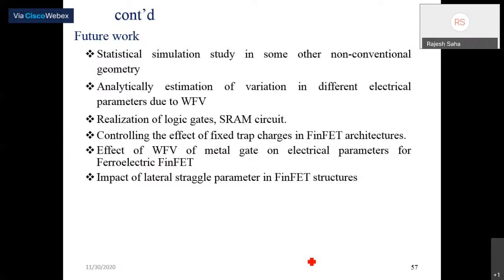See, what does lateral straggle mean? When you do the doping in the source and the drain, then due to some tilt angle and the diffusion process, the source and the drain will extend into the channel, which leads to a reduction in the channel length. And due to the reduction in the channel length, it has a severe impact on the electrical parameters and will lead to variation in your electrical parameters.